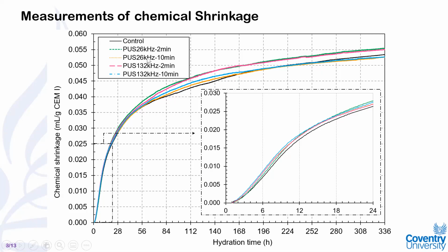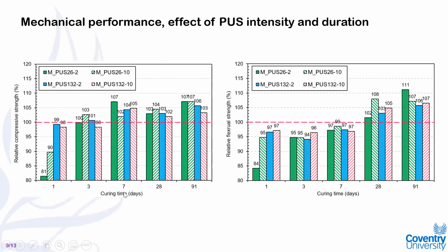But the longer exposure of sonication will lead to lower chemical shrinkage at the end of 14 days with this scale. But in the short term, during 24 hours, you can see the acceleration of chemical shrinkage due to the sonication. Here you can see on the left the compressive strength, the relative index of compressive strength compared to the reference samples,